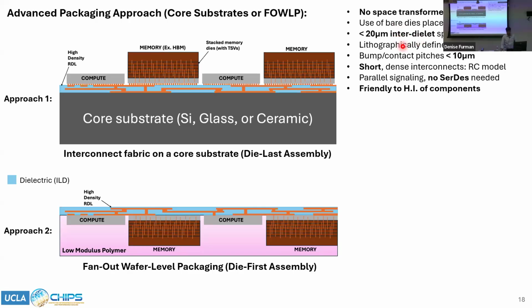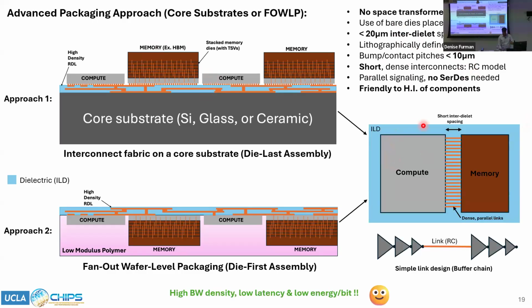And also the wires are lithographically defined, so they can be very fine pitch, less than 2 microns. Bump and contact pitches have been demonstrated less than 10 microns. And because these interconnects are now very short and there are a large number of parallel links, as you can see here, you can treat these links with a simple RC model, like how you would do on chip. And therefore, the design of the driver itself becomes much simplified. And you can drive these links with, for example, a simple cascaded inverter chain.